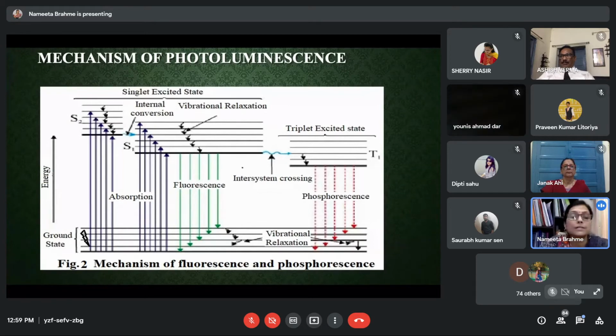This is called the intersystem crossing. Intersystem crossing takes 10 to the power minus 10 seconds to minus 8 seconds. This is where the electron changes spin multiplicity from an excited singlet state to an excited triplet state. So this is the slowest process in the Jablonski diagram, several orders of magnitude slower than fluorescence. This slow transition is a forbidden transition.